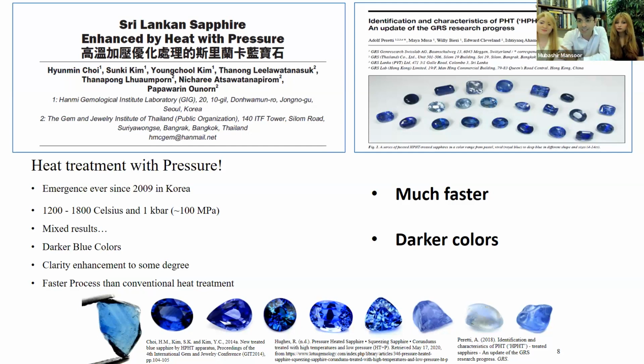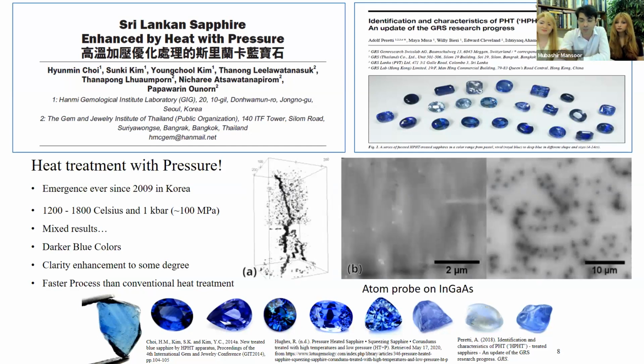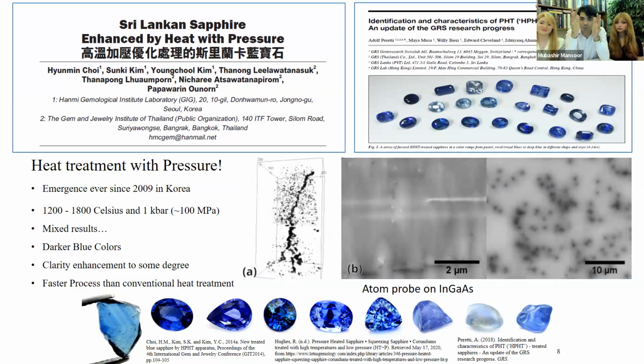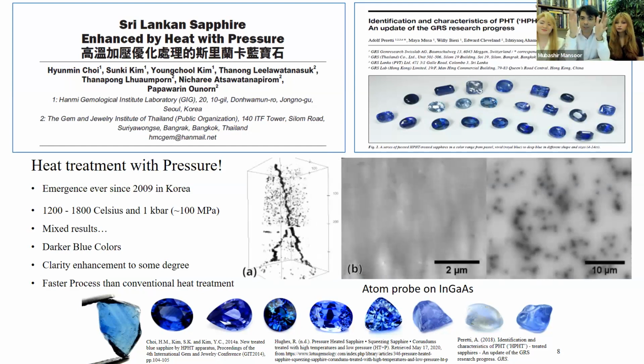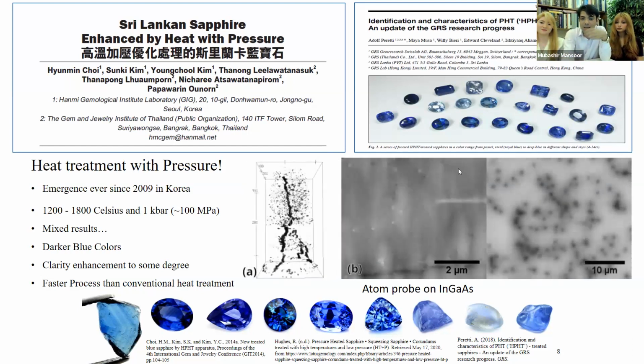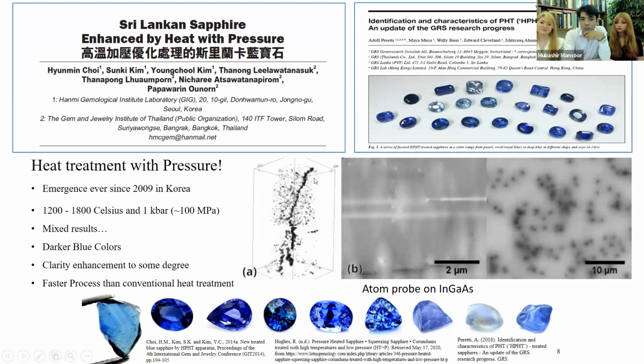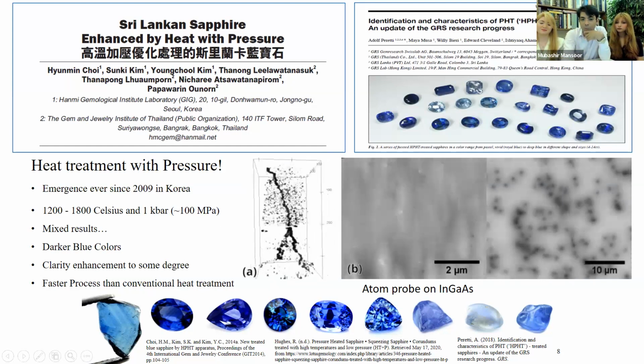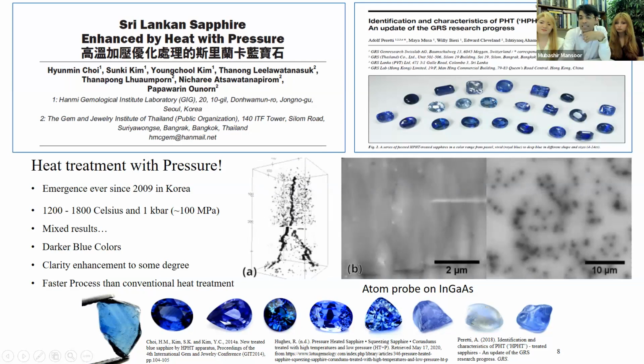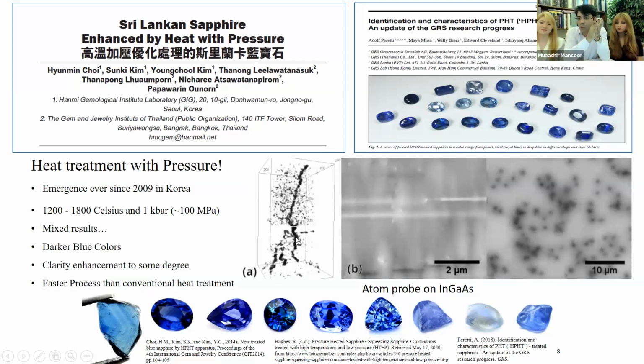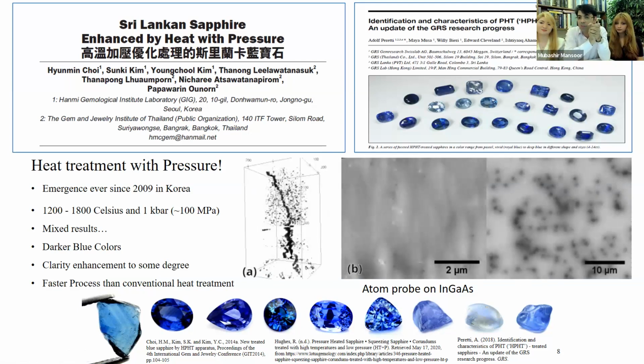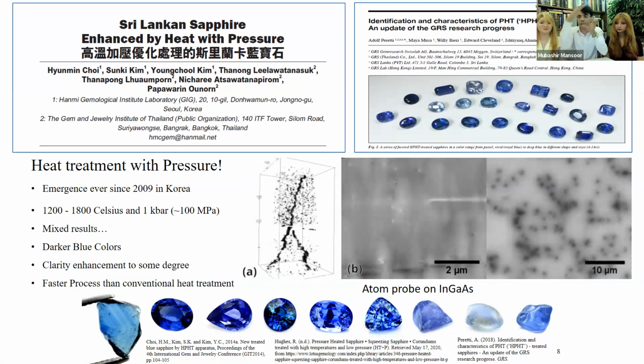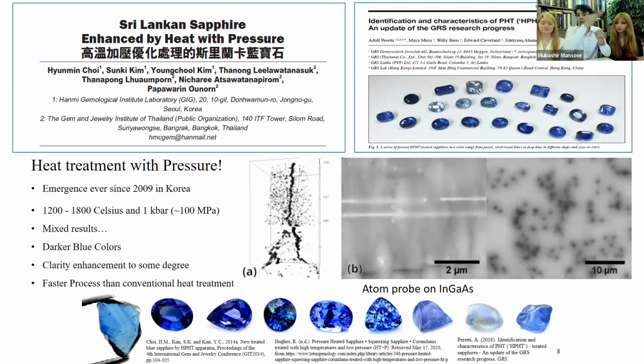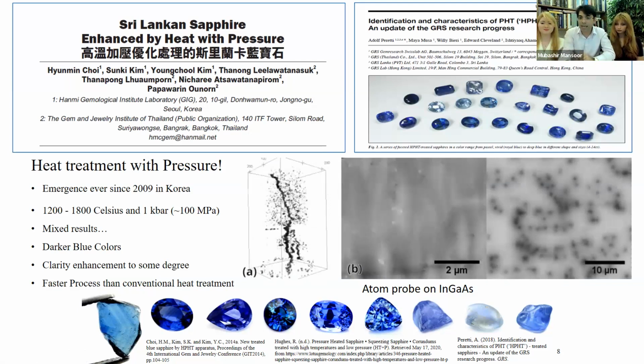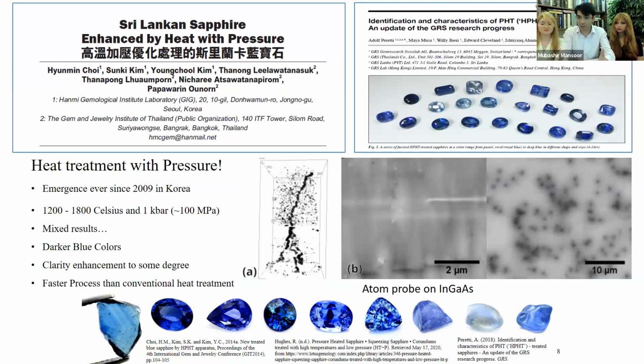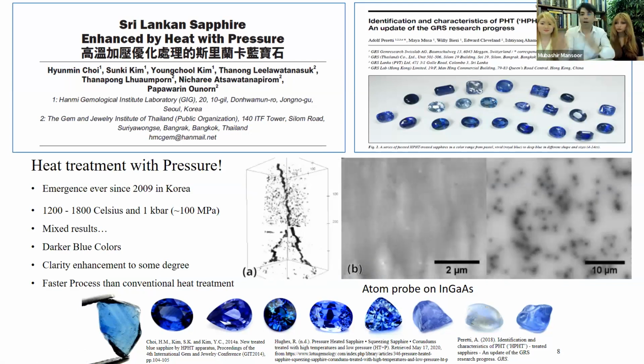However, what's happening here is something that I just wanted to mention. In this case, sapphire is being pressured while being treated. This diagram over here actually shows how a dislocation looks like from an atomic perspective. Dislocations from an atomic perspective are like highways. They create these atomic imperfections that can go all the way from one side of the gem to the other. And they create highways for atoms to move around.